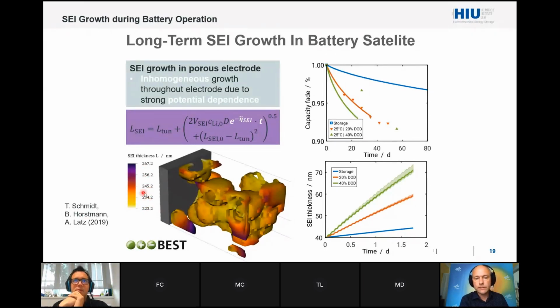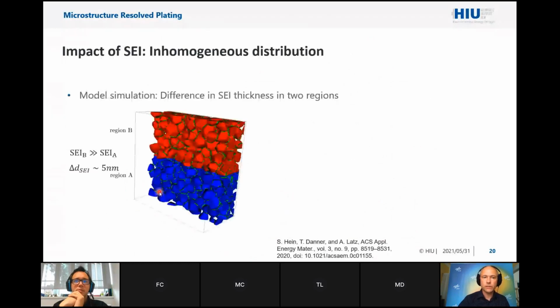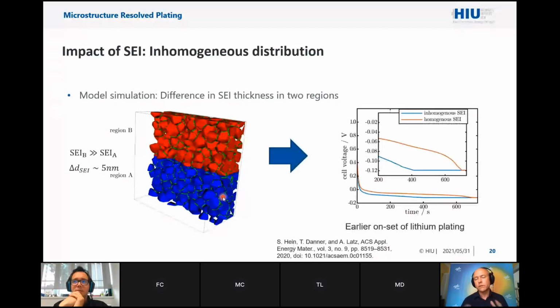And I say this number since what we now did for understanding plating is that we considered what is going to happen if these inhomogeneities of the SEI are adjacent to each other, which we have seen in the previous picture. So we considered an artificial regime, namely a thick SEI and a thinner SEI, with a difference of about 5 nanometers. And then we compared how the plating is going to happen in these two situations: the homogeneous one, which is the orange one, and the inhomogeneous situation.